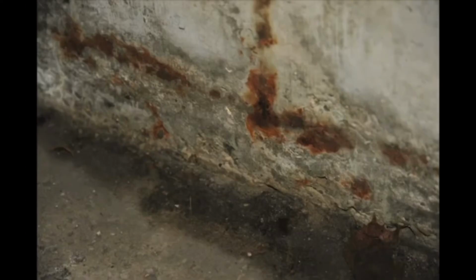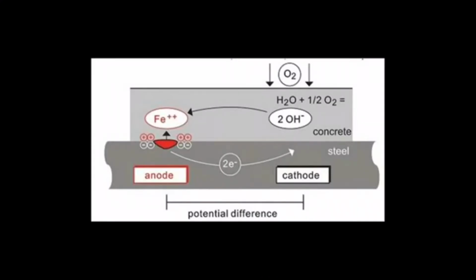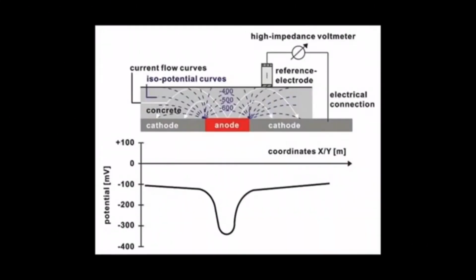The unprotected rebar is then subject to corrosion, which is an electrochemical reaction shown here. This principle creates a potential difference that can be measured by the half-cell method. As the half-cell probe is moved across the concrete surface, the variation in the potentials measured allows the localization of the corrosion hotspot.